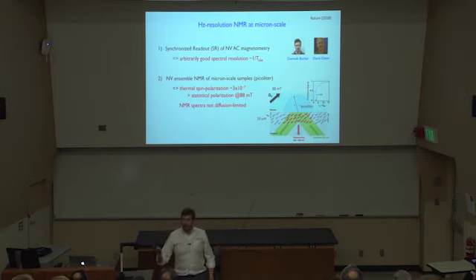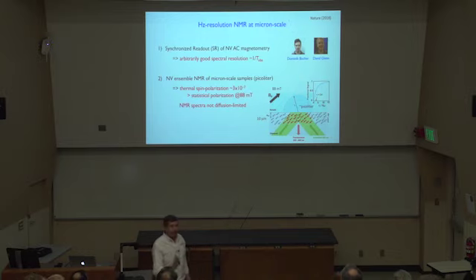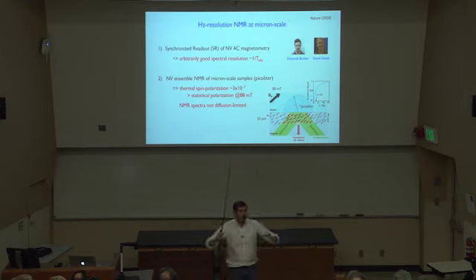It's sort of like win by giving up, right? But the micron scale is still useful. The micron scale is the scale of individual cells. It's too small for conventional NMR, and there's lots of problems where people care about things at the micron scale too. At the micron scale, even in the relatively wimpy magnetic field we used in our first demo experiment of 88 millitesla due to limited equipment, the thermal polarization of the nuclear spins is still greater than the statistical polarization fluctuations, because now you're in a larger sample with more spins, and 1 over square root of n is smaller, right?